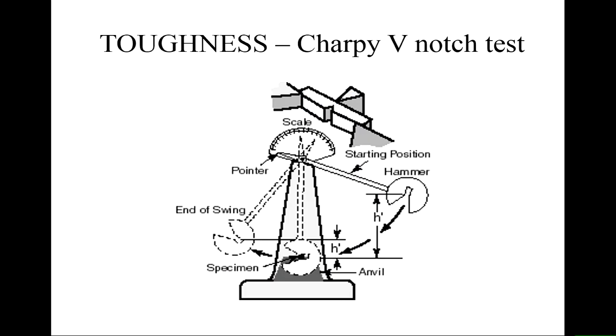So it looks a bit like this. You have a hammer, and that hammer's got a funny shape because you have to make sure it captures the sample and doesn't bounce the sample out of the holder. The sample sits here on the anvil. This comes down and it swings through, and you can see at the end of the swing it's not gone up to the original height, so it's absorbed some energy. What you're doing is a high-speed bending test with a notch on the tensile side.